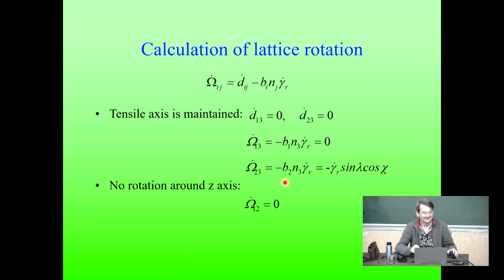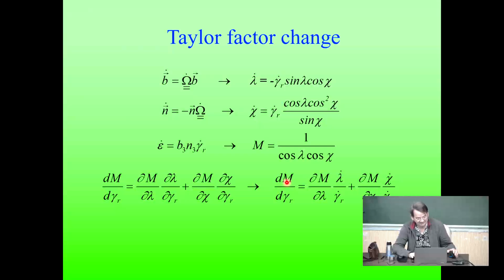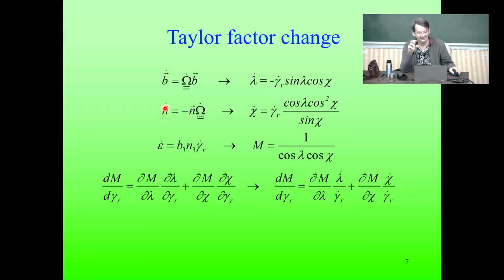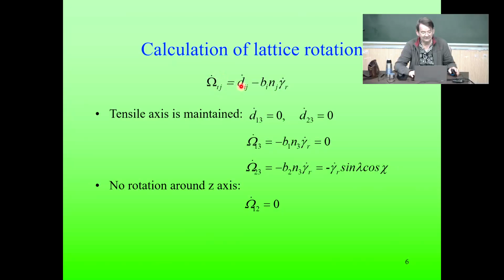It's one of the simplest cases of crystal plasticity calculation. And then we can calculate how the slip direction is changing, how the normal plane is rotating for the slip. And then we can also calculate the derivative of this m. You obtain the m factor, the Taylor factor, which is basically the reciprocal of the Schmid factor for single slip. Here omega dot is the rigid body rotation, and omega dot here is the lattice rotation rate, which is the difference between the velocity gradient imposed on the sample and the velocity gradient made by the slip. That is what leads to the lattice rotation. So this is lattice rotation.